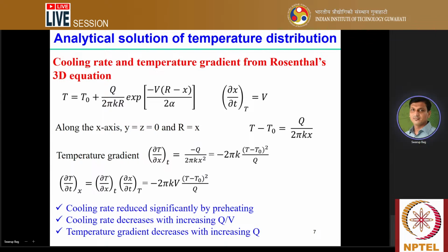At the same time, cooling rate decreases with increasing Q by V. From this equation, Q divided by V indicates the heat input per unit length, and that value sits in the denominator. If it increases, the total value will decrease. Therefore, cooling rate decreases with increasing Q by V value. That means if you increase the heat input per unit length, then the cooling rate also decreases.